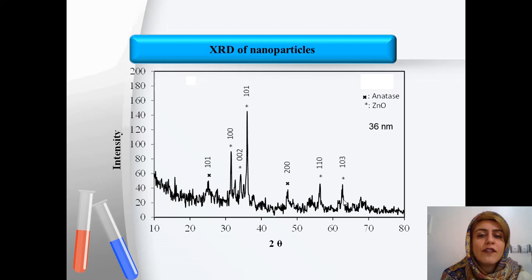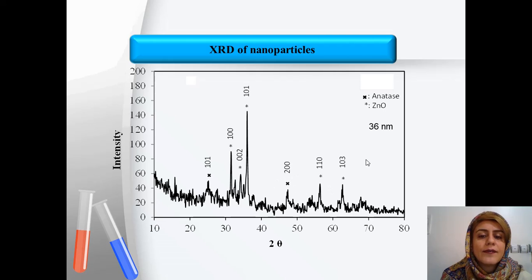As you can see, despite the heat treatment, the rutile phase was not observed; instead, the anatase phase was observed. The suppression of phase transformation from anatase to rutile phase is due to the creation of TiO₂-Zn bonds, which prevents the nucleation of the rutile phase by impeding the titania nanoparticles. Also, the crystalline size of the nanoparticles, obtained by the Scherrer equation, is 36 nanometers.